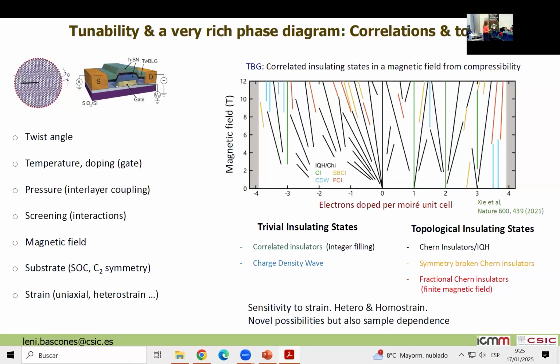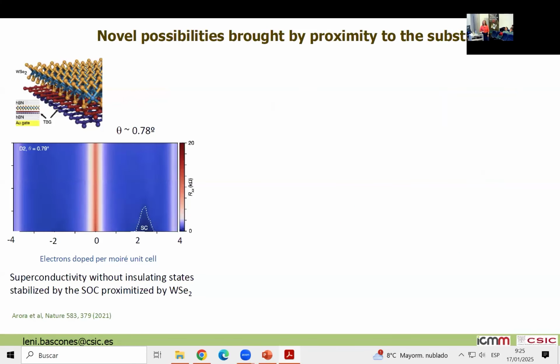At this moment, a lot of states have been observed in many different systems, but there is a lot of sample dependence. It's still not controlled, both due to strain and also to twist disorder and other effects. So we have more possibilities to play with the system, because all this started with this possibility of having this Lego, and then we can play by putting something on top of the twist bilayer graphene.